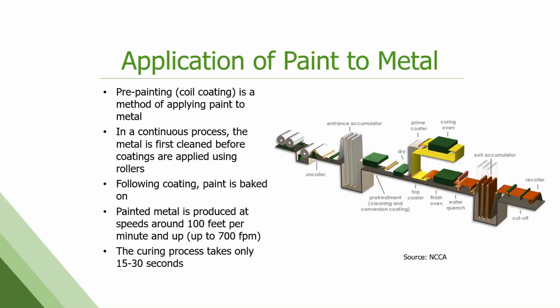So the speeds of these lines are quite fast. Typically 100 feet per minute up to 700 feet per minute. I would say that the average coil line in the U.S. runs at about 300 to 500 feet per minute, so very quick.